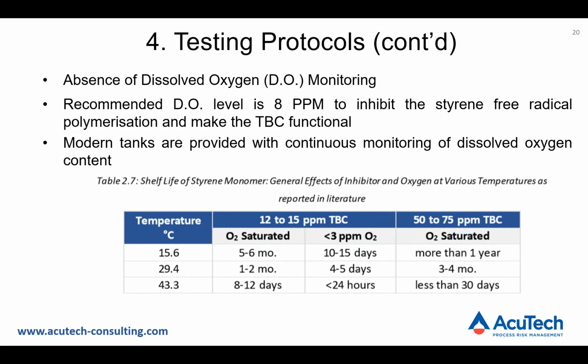So a certain level of dissolved oxygen is desired to inhibit polymerization. You can see from this chart that the level of dissolved oxygen significantly affects the active life of the TBC inhibitor. At least 8 parts per million of oxygen is a key parameter in order to inhibit the styrene free radical polymerization and make the TBC functional.